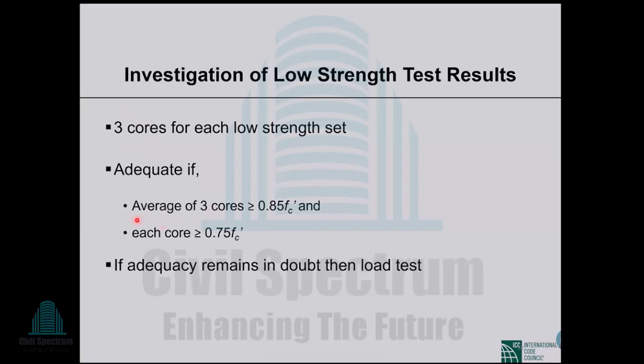And the average of 3 cores, not sets, the average of 3 cores, where 1 core is 1 cylinder, and the standard size of core according to ASTM is 4-inch diameter, 100 millimeter diameter. If the core size is smaller, then this criteria will not apply, because this criteria is too strict if you use a smaller diameter core. There is a lot of literature and there are a lot of standards in ACI, and you have to study those things.